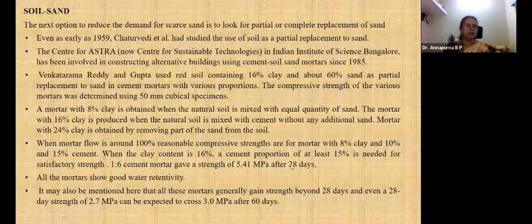So all the mortars here showed good water retentivity because of the presence of the finer particles and clay content. It is also mentioned here that all these mortars generally gain strength between 28 days and more than 28 days. So you have to wait for more than 28 days to achieve greater strength. For 28 days they have got 2.7 megapascal, and after 60 days they have achieved 3 megapascals.